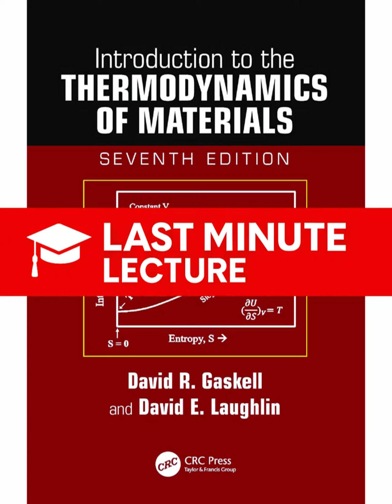And the real power of the Maxwell Relations and the TDS equations is that they transform this whole theoretical framework into a measurable, usable science. They connect theory to the lab bench. And as a final thought for you to mull over, the fundamental math actually constrains the physical world. Remember that relationship we found? The one connecting the curvature of the Gibbs free energy with respect to temperature? Yeah, the second derivative. The partial squared of G with respect to T squared at constant P equals minus Cp over T. So, because heat capacity, Cp, must always be a positive quantity, which it must,